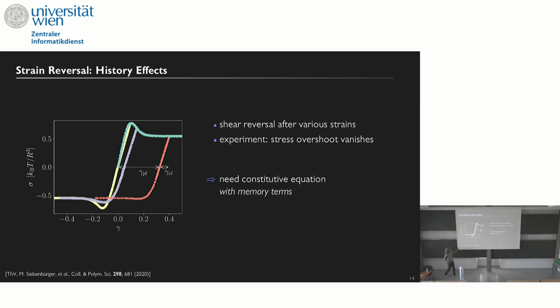And then eventually you reach a stationary state where the stress no longer changes with the strain, then the system is fluidized. And then if you decide, let's say at a strain of 0.4, I revert, and I just take the same shear rate but backwards. You measure the continuation of that curve, so the accumulated strain goes backwards, but the stress overshoot, for example, is gone.